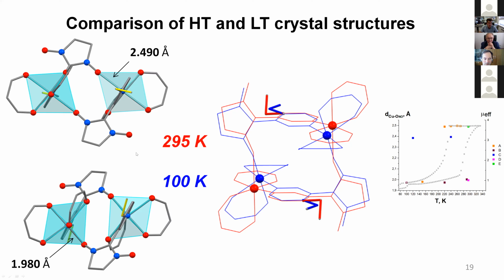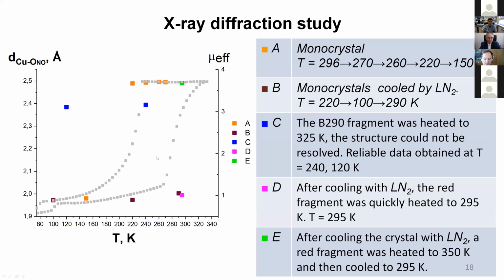In subsequent experiments, we cooled several crystals of the complex with liquid nitrogen and subsequently heated them to higher than 300 Kelvin. For one of the fragments, it was possible to obtain X-ray structure experimental data. The results of these experiments show that the crystal structure of these samples corresponds to the data obtained previously experimentally at 150 Kelvin.